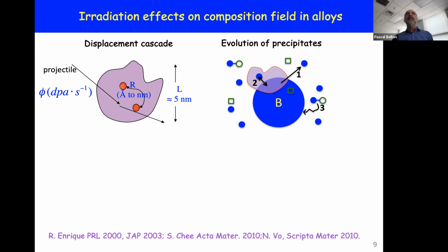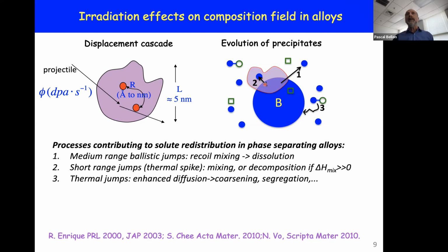In that displacement cascade, if you think about it as a hot liquid for a picosecond, as I mentioned earlier, this process here may also lead to redistribution of the atoms, sometimes maybe inducing dissolution if the material has a somewhat low or reasonable intermediate heat of mixing.